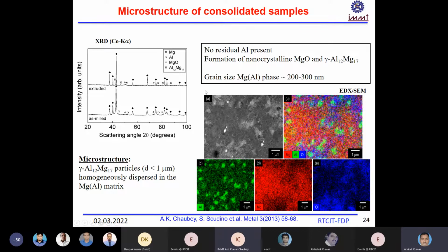And then it was hot consolidated by hot pressing and then extruded. You can see the microstructure now. Earlier in the cast structure, you have seen that the gamma phase are along the grain boundary, but here you can see the gamma phase are mostly distributed. You can see here in these color pictures, this elemental distribution map. You can see the aluminium and magnesium phases, and this gamma phase are submicron size, less than 1 micron or 0.5 micron, 0.2 microns size.